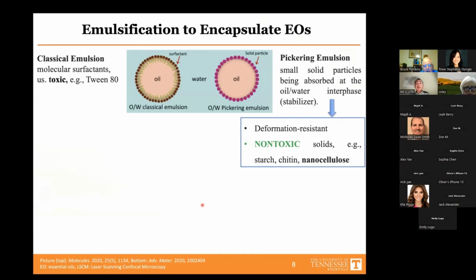properties. So the first example I want to share with you is that we're trying to make an emulsion to encapsulate essential oils. For those of you not familiar with emulsion, basically it's two incompatible phases, for example, either oil in water or water in oil. If you blend it and chill it quickly, it will form an oil in water emulsion. To form an emulsion, you usually need a surfactant, which is a surface active agent, which means that it's amphiphilic. It can help you to disperse the oil and to form this oil and water emulsion.